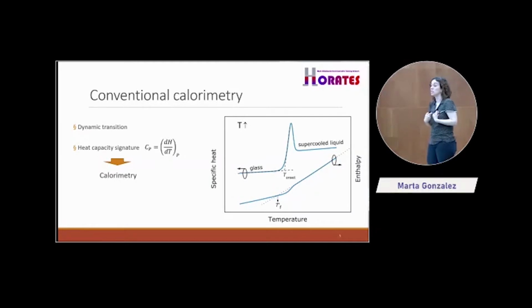What we can do to study our systems: we are not able to measure enthalpy directly, but we are able to measure using calorimetry. I will explain it later. Using calorimetry, we are able to reach the specific heat. Everyone knows that specific heat is the heat that we need to provide the system to heat it up 1 Kelvin, okay? That's it. So from that, in this kind of measurement, if we derivate, well, in fact, it's the opposite. If we integrate the specific heat curves that we are able to measure with calorimetry, we recover these enthalpy curves, and from here we get a lot of information about stability, etc.